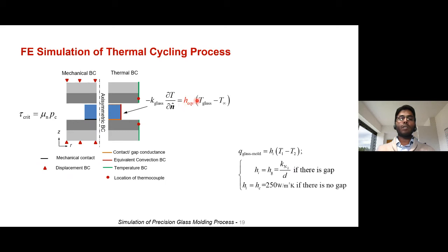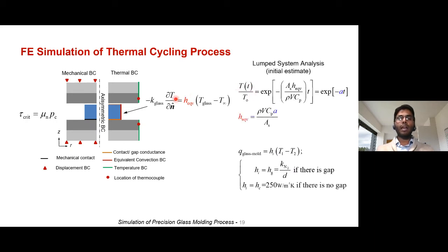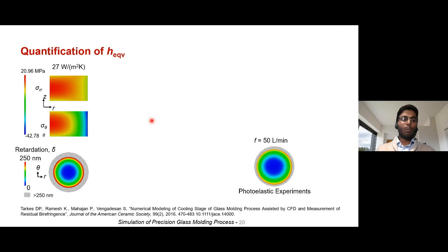For this heat transfer coefficient we do not have any initial value, but what I did is I used a lumped heat transfer analysis, which the bachelor students might have studied in their heat and mass transfer subjects. So using this lumped system analysis, I have the temperature as a function of time and the initial temperature information from the experiments. By doing a curve fitting, I'm able to compute this exponential constant A, and this A is related to all the geometrical and physical properties of the glass, which are already known. So from there, I can estimate the initial value of the heat transfer coefficient. And based on this, I gave it as input to the finite element simulation.